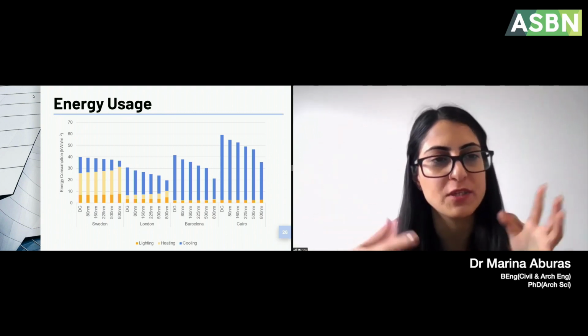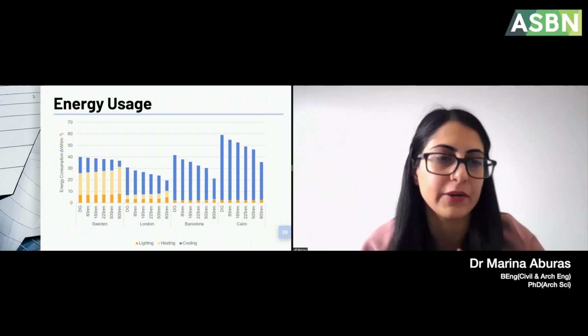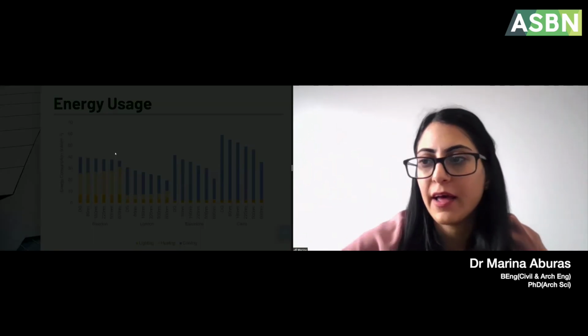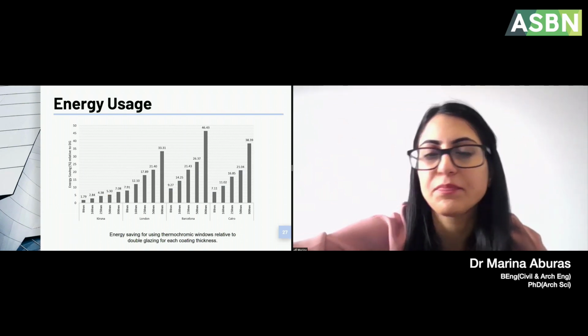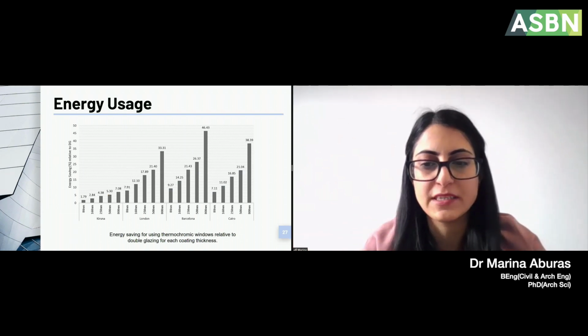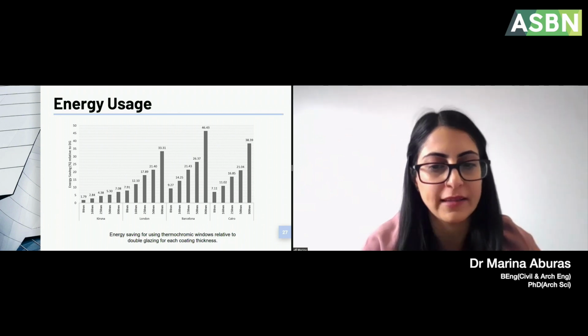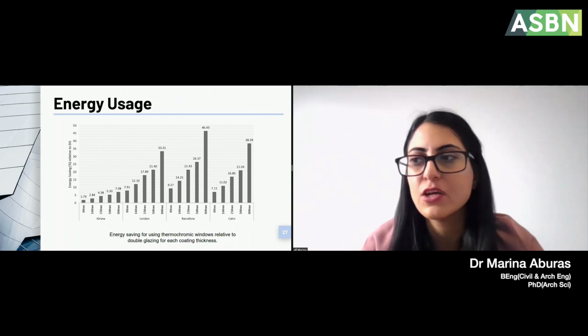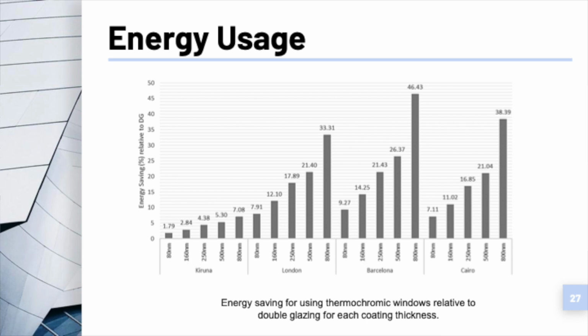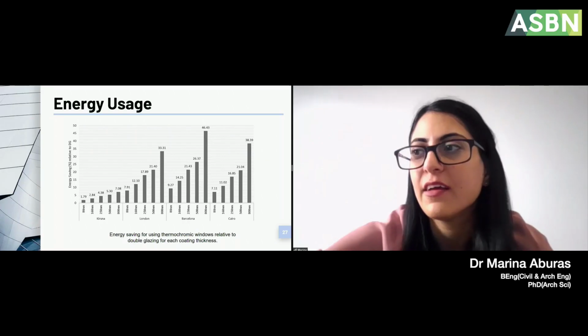So it's that trade-off between what you need for that particular climate. And another way to look at that is looking at energy usage in particular compared to a double glazed window for each of those coating thicknesses. So you can see that the results show, like we were seeing earlier, that the thicker films show the highest energy saving over double glazing in all of the climates. And that's due to a combination of both visible and IR effects. But that's most prominent for the thicker coatings in Cairo versus, again, Kiruna, where you see less of that benefit.